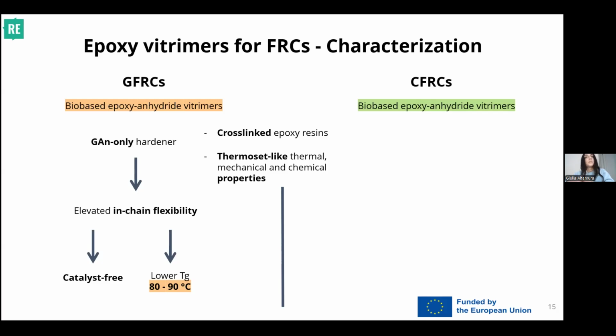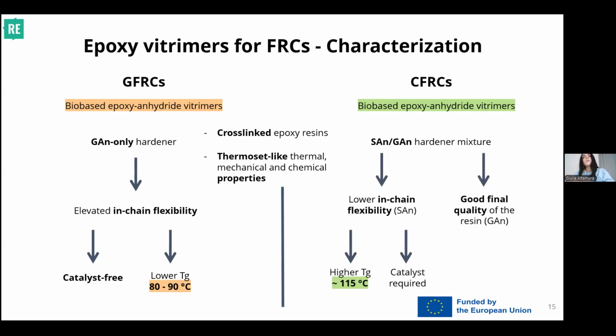But flexibility in polymer chemistry also means a lower Tg. So our Tg is around 80-90 degrees, meaning that it's typically more suitable for less performing composites, such as glass fiber reinforced ones. On the other side, the mixture of anhydrides gives us a lower flexibility that gives us, in turn, higher Tg, but we need a catalyst, TBD indeed.